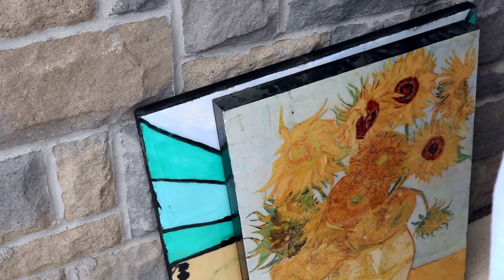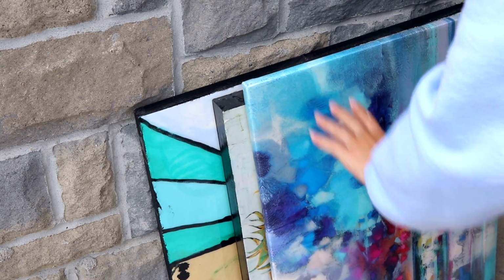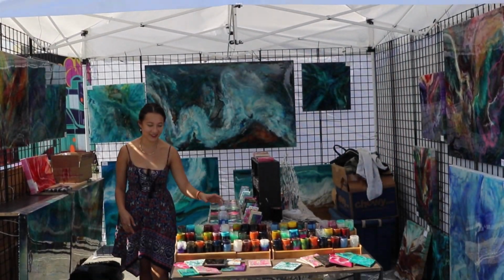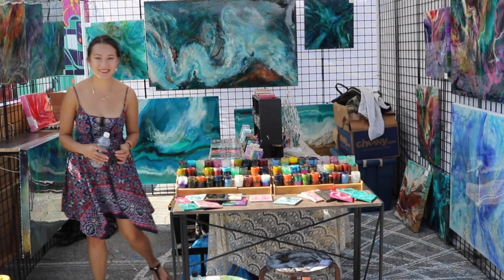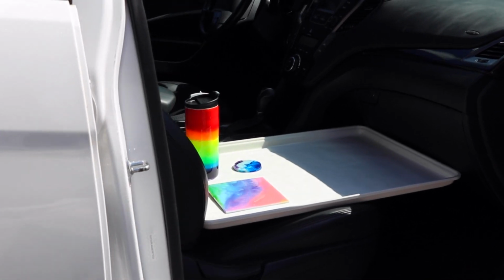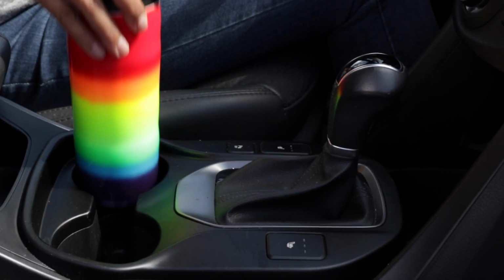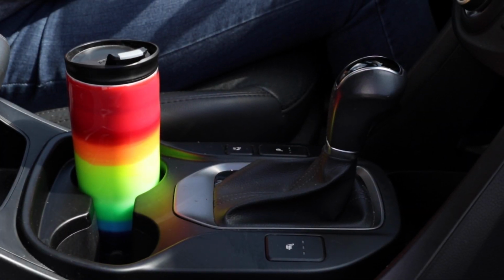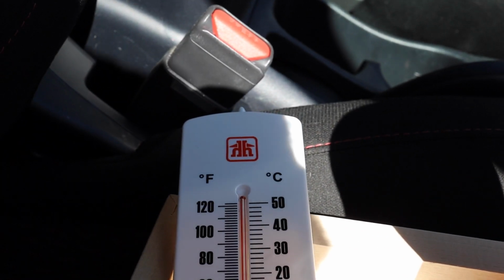Care must be taken not to stack up or lean artwork against each other if, for example, you're showing your work at an outdoor art festival. Never leave cured resin art, including tumblers, inside of a hot car during the summer months. In these conditions, the temperature can get exceedingly hot. Gravity may pull the softened resin, causing it to pool or warp irreparably.